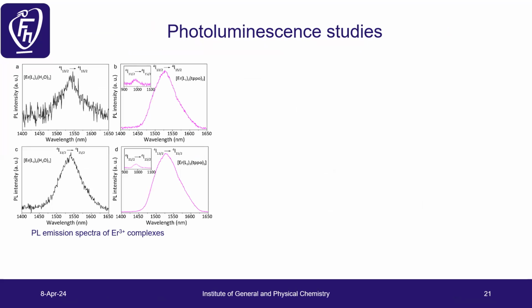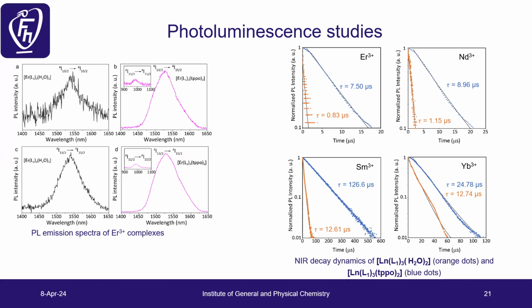Okay, so for the quenching effect, this is most prominent and seen on erbium, near-infrared. So here is an example: we can see erbium at 1.5 microns emission with 2 water coordinates, and when we introduce the triphenylphosphine oxide, we can see the intensity increase. But also we can see this in lifetimes. We can see that from 0.8 we go up to 7.5 microseconds, or 1.5 to 8, or for samarium from 12 to 126. But only for ytterbium we see just 2 times, not 10 times more.